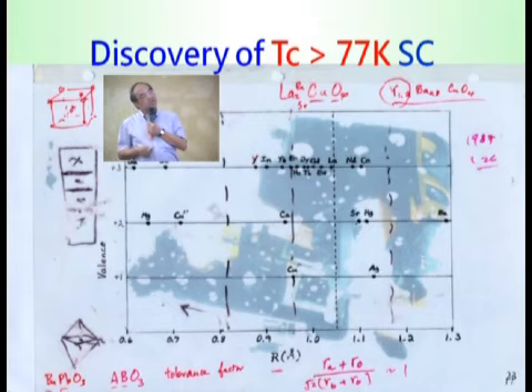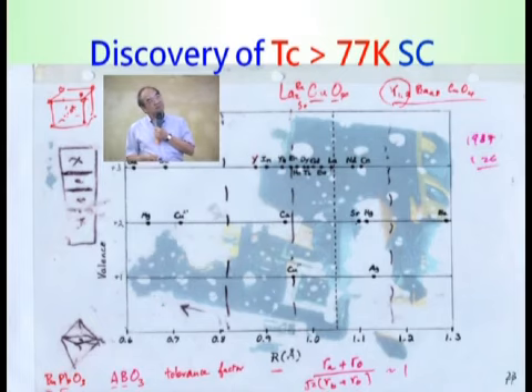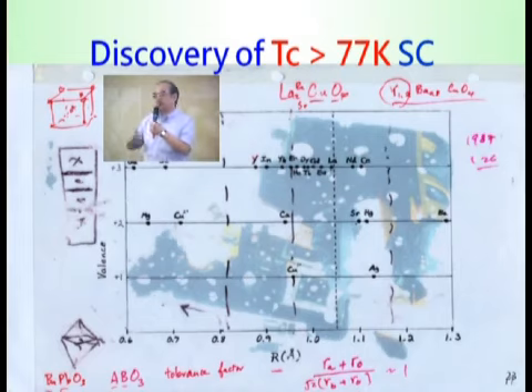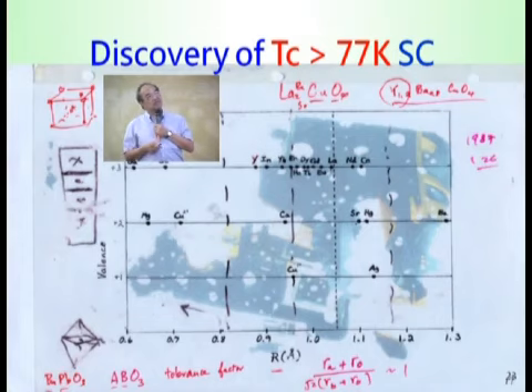And by looking at this chart, we said, well, why don't we just mix this yttrium and the barium? Right? If you look at this distance from here to here, it's almost equal to that. So essentially, you get a 1-to-1 ratio in terms of size. Then you might meet this perfect line. Right? So we did some calculation, and that was the number we came up with and said, well, let's try the